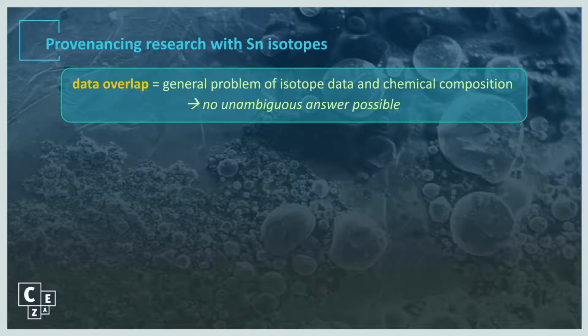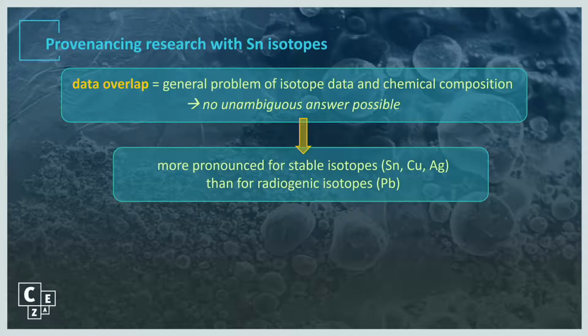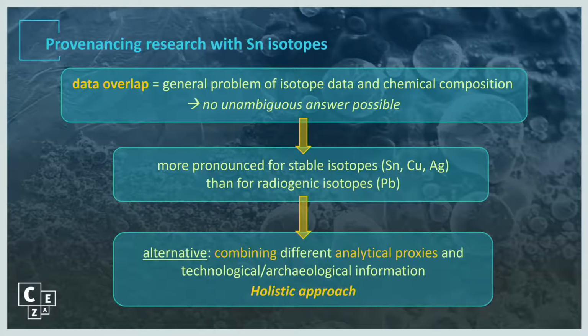Okay, data overlap, we all know, is a general problem of isotope data and even chemical composition, so there's never the possibility for an unambiguous answer to the question of provenance. This is more pronounced for stable isotopes like tin, copper, and silver than for radiogenic ones like lead or osmium. And that's why we tried to find an alternative application of the stable isotopes, especially of tin isotopes, for getting more information out of the material that we analyzed, which is beyond the mere question of provenance. So the alternative was simply combining different analytical proxies, different isotope systems, with chemical composition, with technological and archaeological information. So this is what I would like to call the holistic approach.